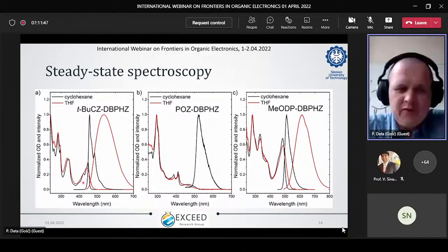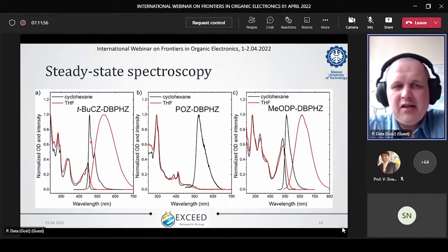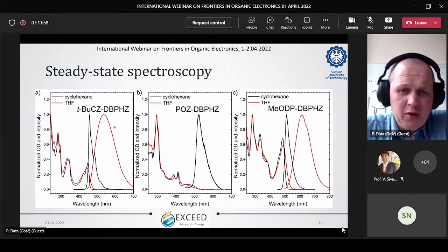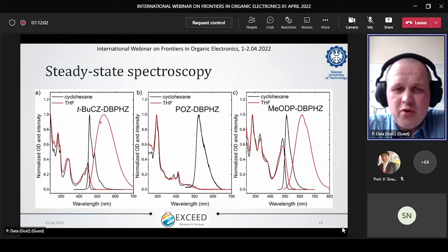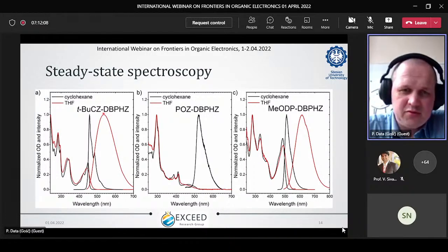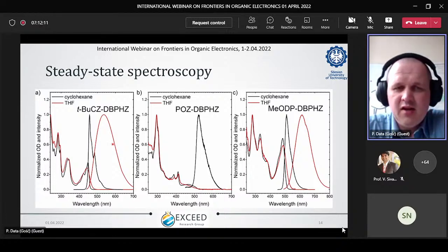In the non-polar solvent, we should have a very nice, very narrow emission, which is usually associated with the localized excited state. But if you move to the polar solvent, like here in the red, then we have very broad emission, single exponential emission, which is associated with a charge transfer process. So this is the charge transfer state.